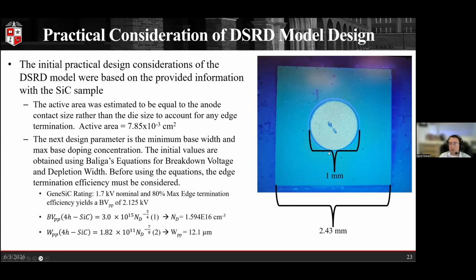And then the next thing we could do is begin to estimate the minimum base width and max base doping concentrations to use in our simulations. So with this, I used Baliga's breakdown equations for both the breakdown voltage and depletion width in order to calculate that. Assuming an edge termination efficiency of about 80%, we end up with a parallel plane breakdown voltage of 2.125 kV. Plugging that into the equations from Baliga, we end up with a base doping concentration of about 1.6 times 10 to the 16 per centimeters cubed. And we end up with a parallel plane width of about 12.1 microns.